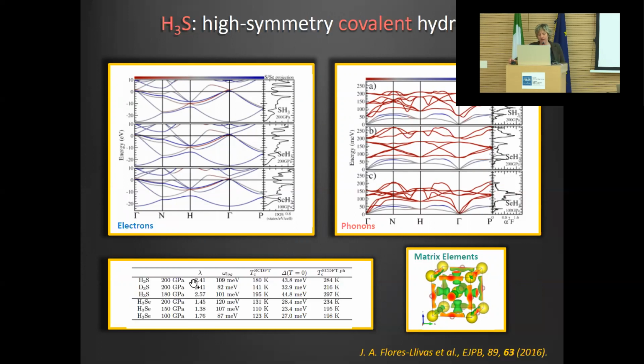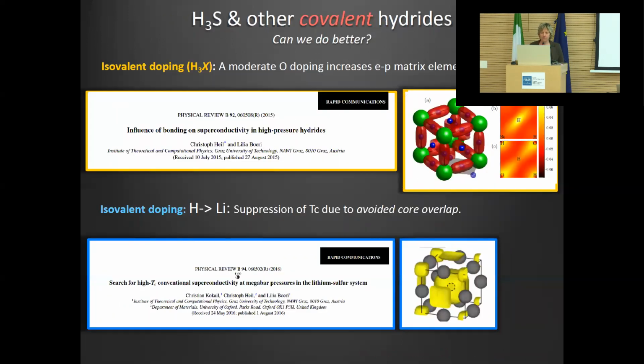and indeed this also shows that you have a very large lambda. And the very large lambda, I mean, the thing that really explains why you have this very large lambda is this kind of picture where we said before you have these covalent bonds between hydrogen and sulfur. And basically the way in which you understand this large lambda is that you must imagine that if I move the hydrogens around the equilibrium position, then these strongly directional bonds will distort, and basically a lot of charge, a lot of electrons will move around, and this is shown by this very large value of lambda here. So this is the starting point.